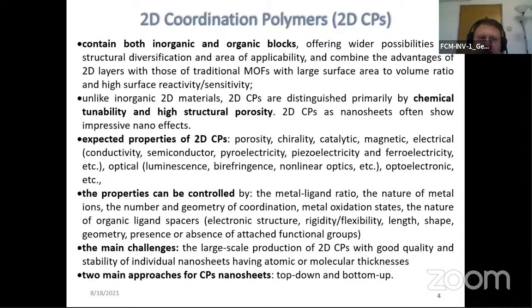The main challenges related to these materials are the large-scale production of coordination polymers with good quality, good stability of individual nanosheets. There are two main approaches used for exfoliating the stacked two-dimensional polymers, top-down and bottom-up. I will show here several two-dimensional coordination networks recently obtained, in which the interpenetration of the layers and the interaction between them are avoided and limited by the use of appropriate ligands.